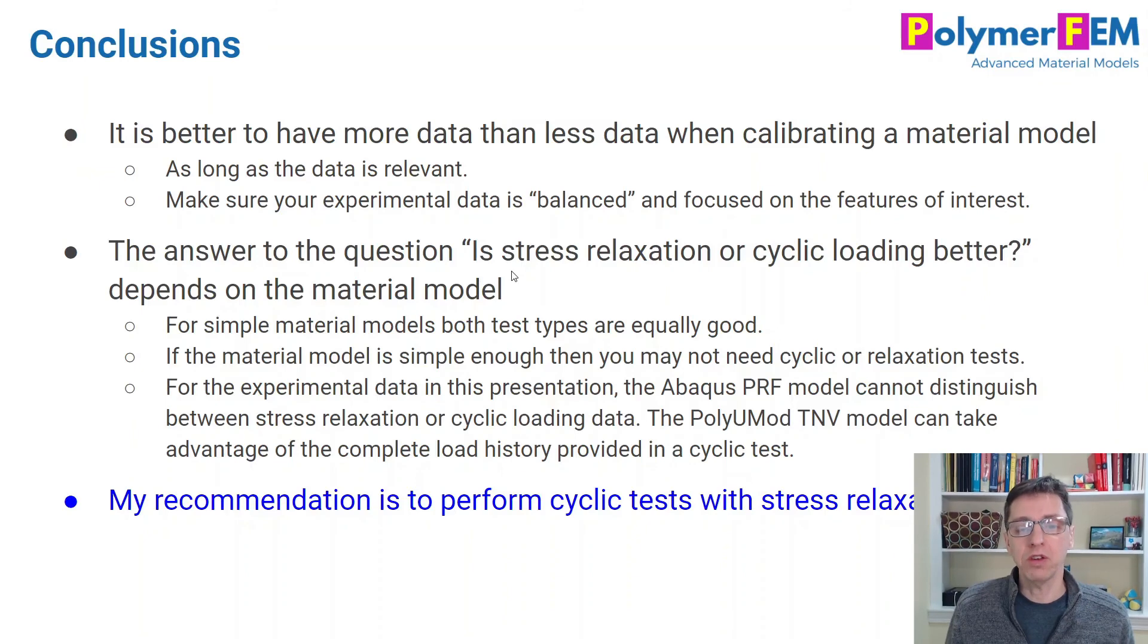So back to our original question: is stress relaxation or cyclic loading better? We need to remember that when I say cyclic loading here, I'm really talking about cyclic loading with relaxation segments in it. And I would actually prefer that still because it gives you the unloading response as well. Stress relaxation is fine. In some cases, it doesn't really matter if you have the unloading or not. It depends on your material model and if the material model is accurate enough to capture the difference between loading and unloading. But if you want to be safe, I would certainly do this type of cyclic loading with stress relaxation segments in it. That's the recommendation I have.